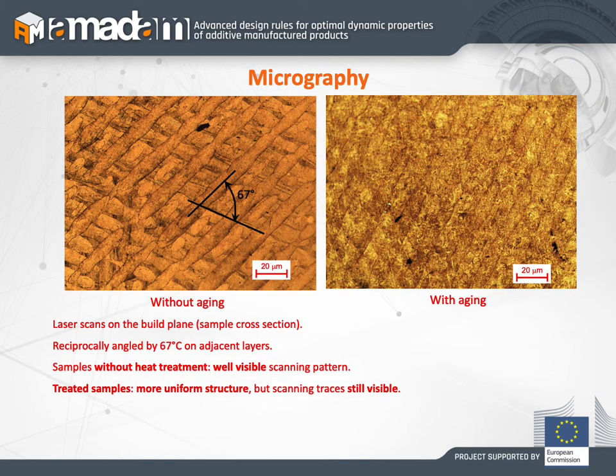And here you can see the micrography of one layer of the beam, and you can see also the directions of the beam that are inclined of 67 degrees each, without aging on the left, with aging on the right. The macrostructure is different due to the fact that the material has been subjected to the aging. In the sample without heat treatment the scanning patterns are well visible, whereas in the treated specimen there is a more uniform structure, and the scanning is still visible, but the structure is really more uniform.